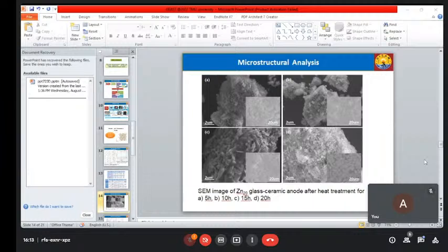Then I prepared an active material there. I coated the synthesized glass, used sodium foil, and made coin cells in my laboratory, and then I tested them using a battery testing device. So this is my anode network. I already told you that I went for DTA and XRD results. So I got the glass transition temperature and the crystallization temperature for all my samples, and then I went for XRD analysis also.